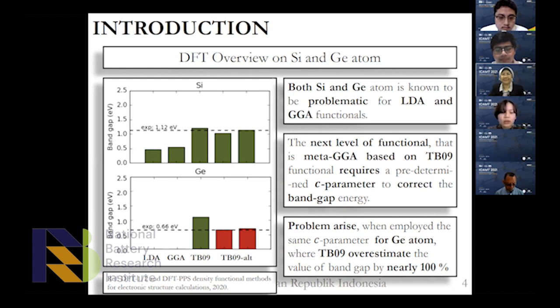Furthermore, it is also known that TB09 requires a predetermined C parameter to correct the band gap energy, which produces more uncertainty for the study of germanium systems. Thus, in this study, we try to use another meta-GGA functional known as SCAN, or strongly constrained and appropriately normed, which has been successful in opening a proper gap for insulating cases.